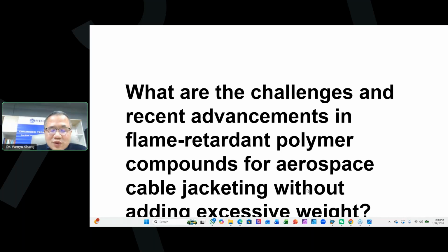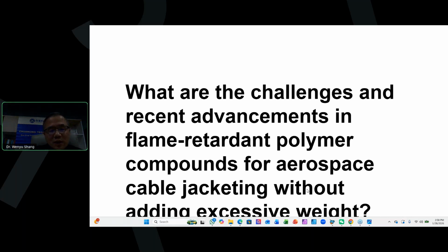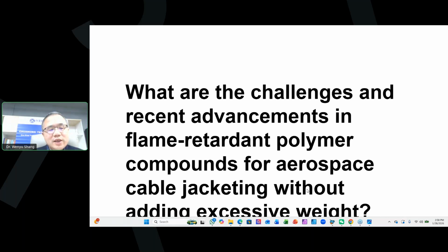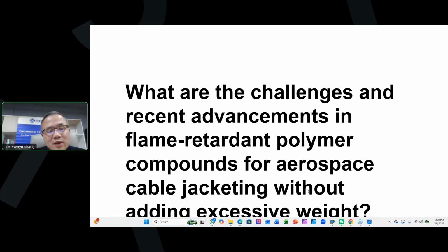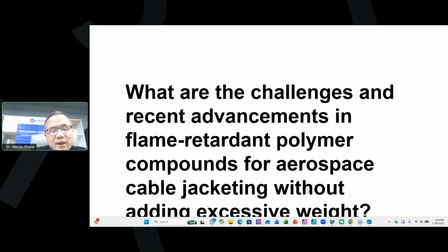Of course, for the very high temperature resistance cables, in our case mentioned today, you don't want to expand the size of the cable too much. So the communication cables deployed in the airplane are usually very thin cables. You don't want to make the insulation layer too thick, which causes the whole cable to have a much larger diameter. So, back to the insulation polymer, you want the polymer to be highly FR resistant and highly heat resistant, while at the same time it can perform as a dielectric insulation material to make the signal carrying high quality. Okay.